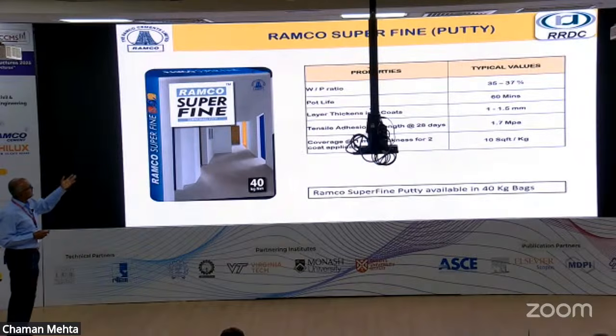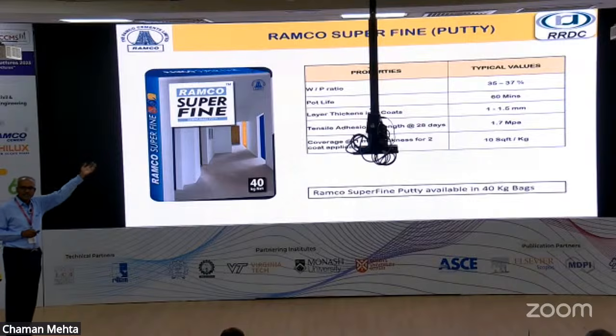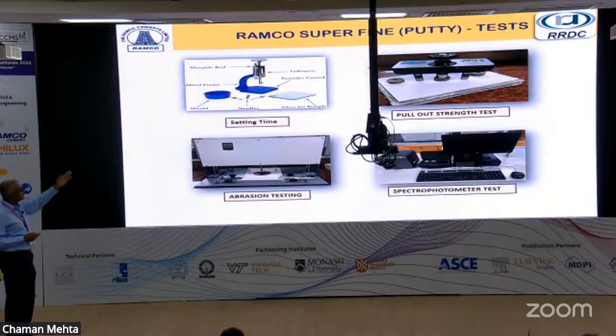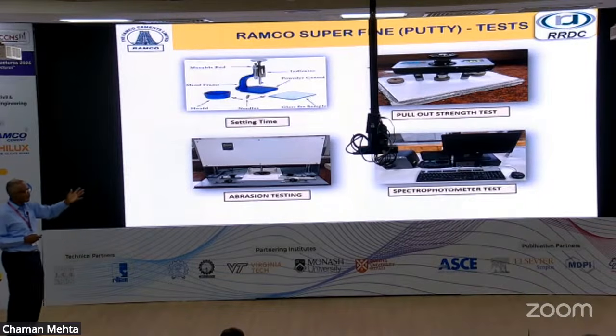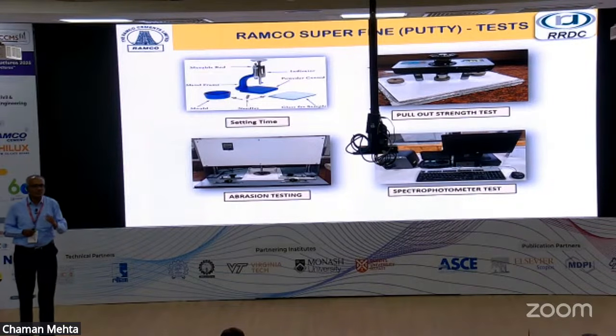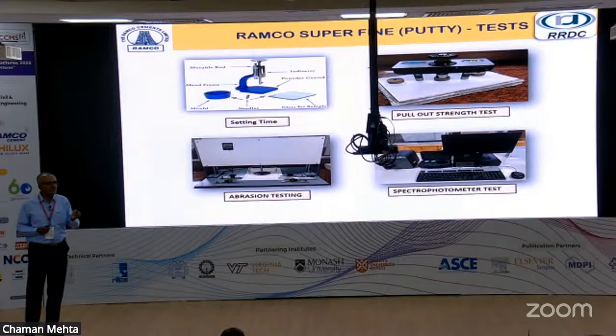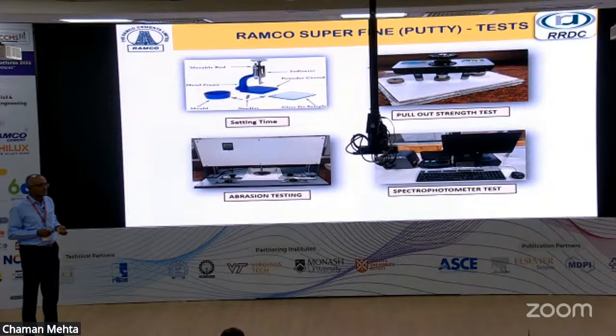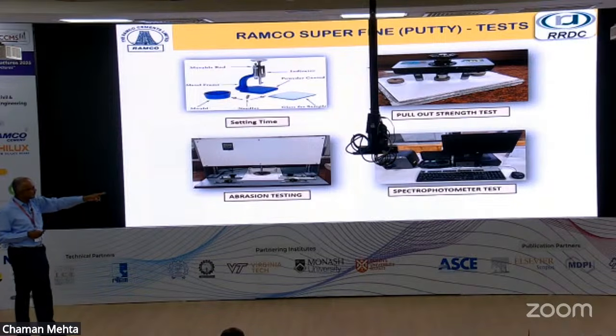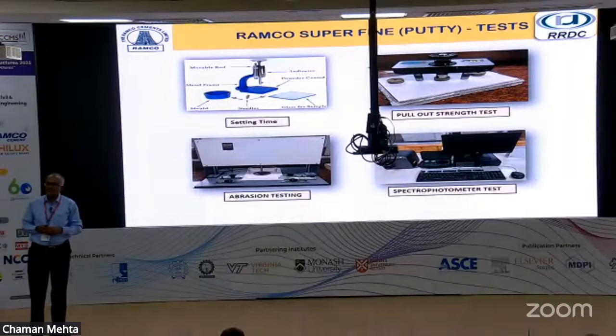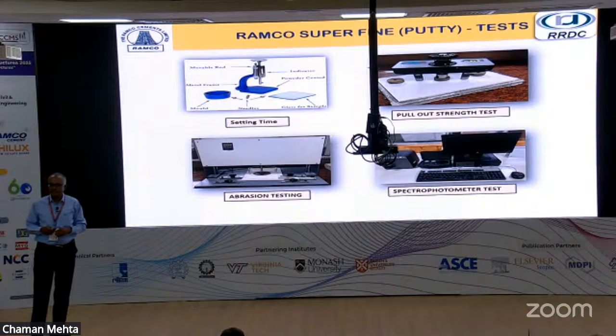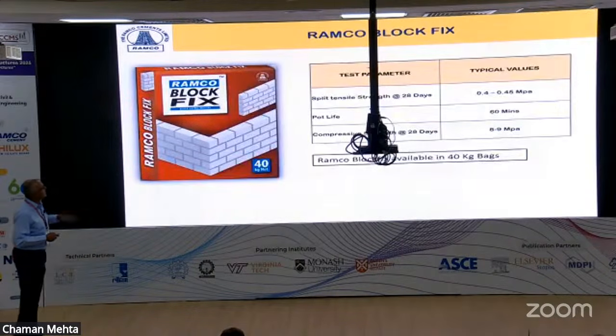Superfine putty, again a common product that is available in the market, and we have had this for a number of years. So tensile adhesion strength is one test that we do for this. Setting time, pull-out strength, because you will see that pull-out strength is a common test for most of the products, because being a thin membrane, you have to do the pull-out strength test for most of these products. So we have that. The spectrophotometer test is one test which tests the degree of whiteness of the putty itself.